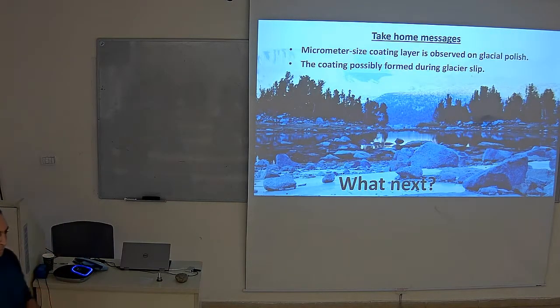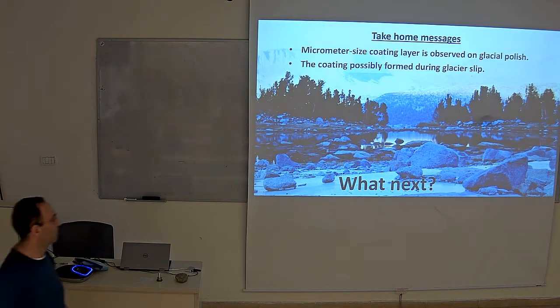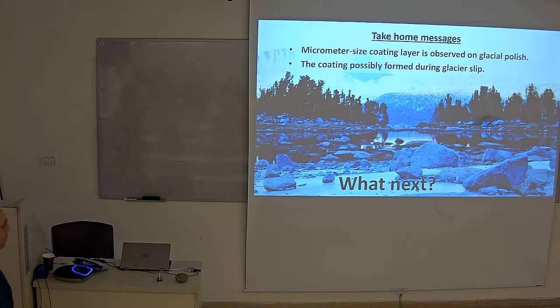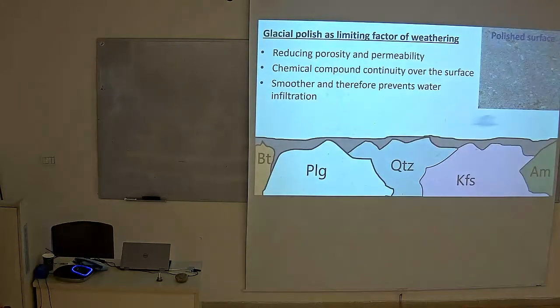Okay, so the take-home message from the results is that we have a micrometer-size coating layer that is observed on top of the glacial polish, and that the coating is possibly formed during glacial sliding. What are the next steps we are taking there? In terms of chemical weathering, we are trying to understand why it's resistant and what we can learn from it. So what's happening is actually reducing the porosity.